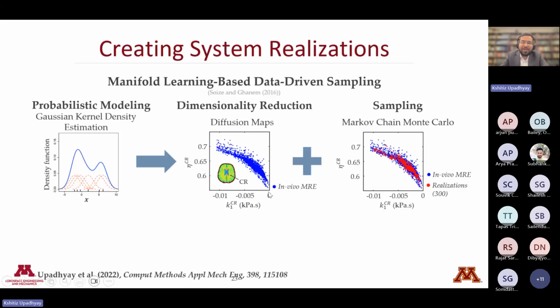The left-hand side plot shows the distribution of two model parameters, eta and k1, which are two parameters of the corona radiata region. You can see these are all the data points, one point for each data point on the brain tissue. And the structure is complex, right? It's not a very straightforward structure. This is actually a 4-dimensional plot, so I can only show you a 2-dimensional projection. This is the data that comes directly from our experiment, from in vivo MRE.